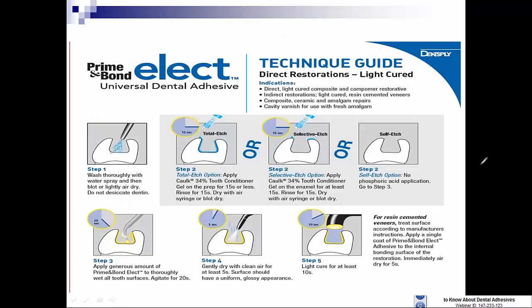So if we look at the Prime and Bond Elect, this is an acetone-containing universal adhesive system, we would want to focus on a couple of areas. Number one, if we etch, we only want to etch 15 seconds on dentin, no more, but no less than 15 seconds on enamel. Now, I want to highlight the bottom left box where we apply generous amounts of this material, this is an acetone-containing material, and thoroughly wet and agitate for 20 seconds to allow full penetration. And this would be whether the dentin is etched or whether we're using a self-etching technique.